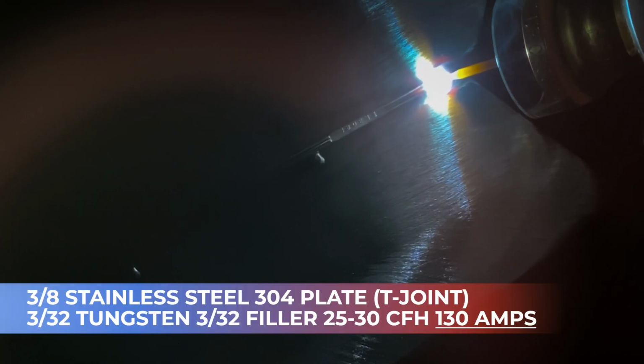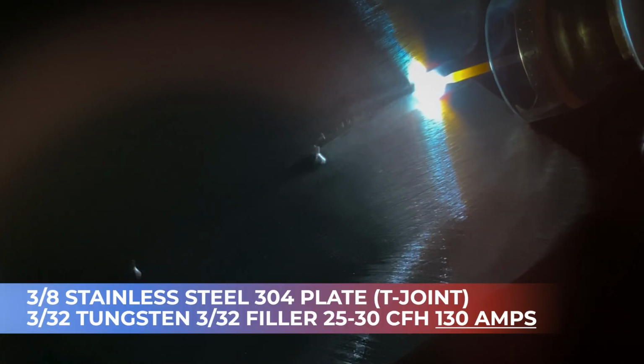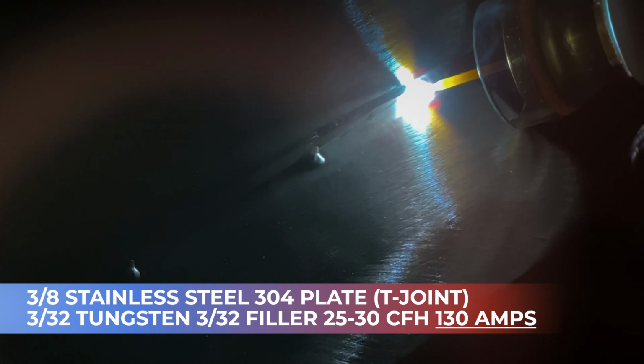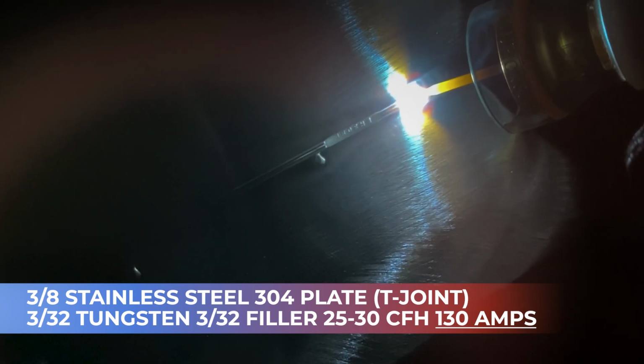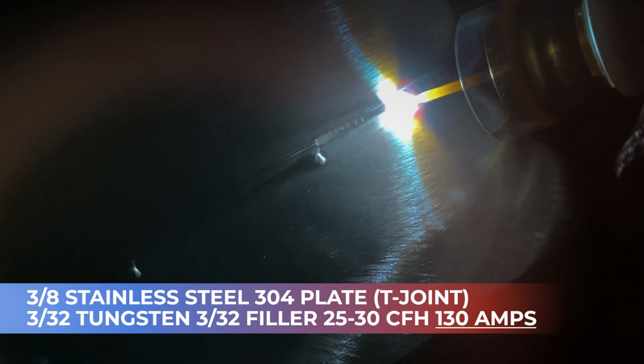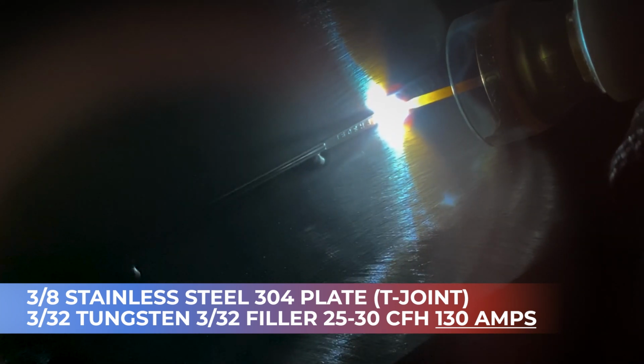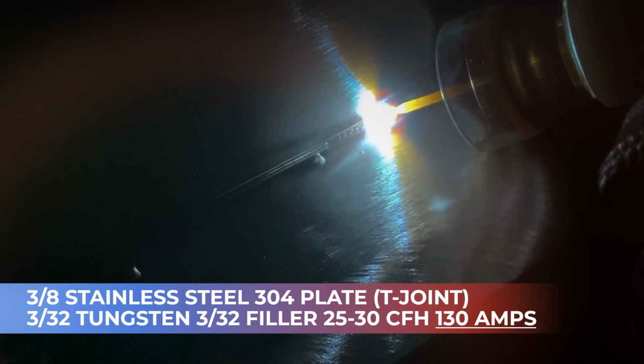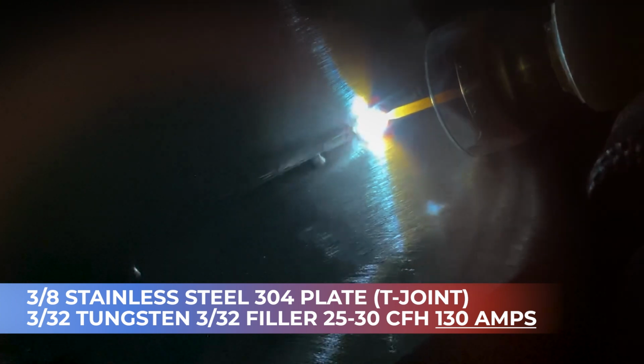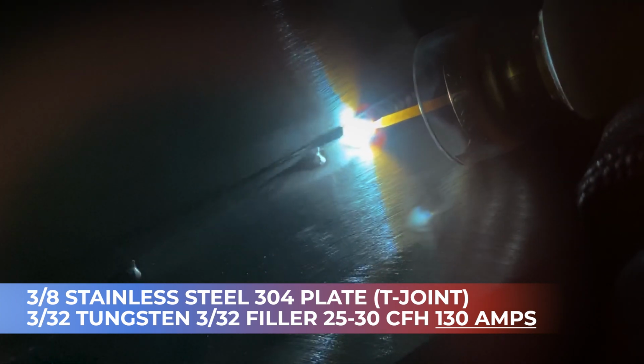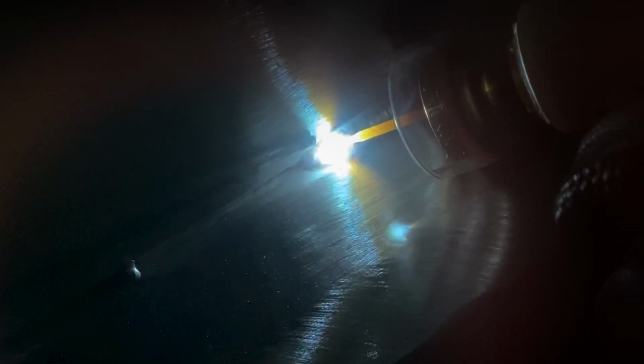All right, y'all. So as you're about to see, we're rocking 3/8 stainless steel 304 plate, running a T-joint here. And I'm starting out with 3/32 tungsten, 3/32 filler, and I'm running 25 to 30 CFH at 130 amps. And you can see as we're going through here, my travel speed's very slow. It's taking a long time for the base metal to heat up enough to be sufficient enough and create the right environment for me to add filler and create a good weld.